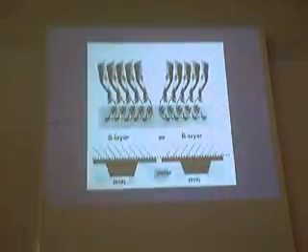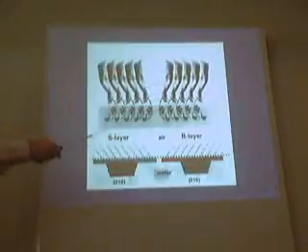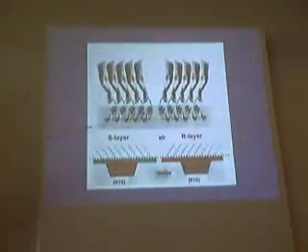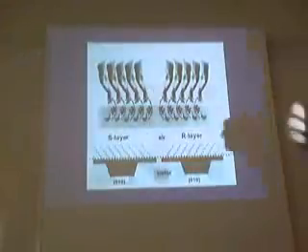And this is what we found, that if you have these ends here, they can organize the molecules which are in the water, and they can start crystallizing. And what we have found by this diffraction method is that this layer here is very similar to the first layer of glycine, as we proposed experimentally on the basis of the orientation of the glycine crystals in the system. Okay? So this was the first part.